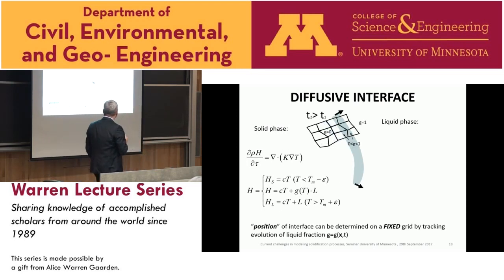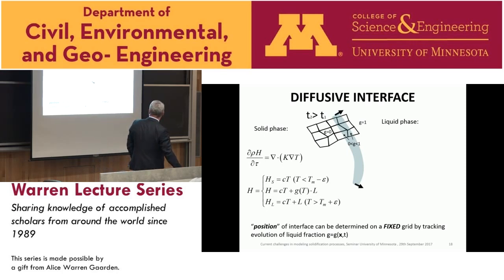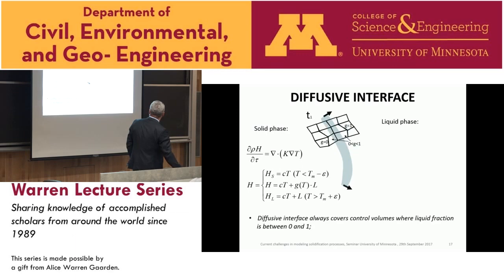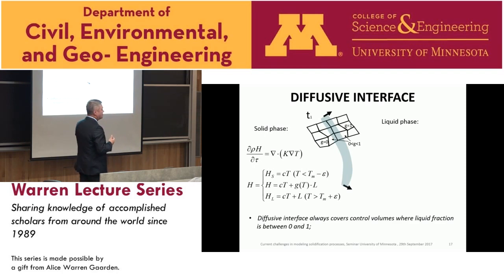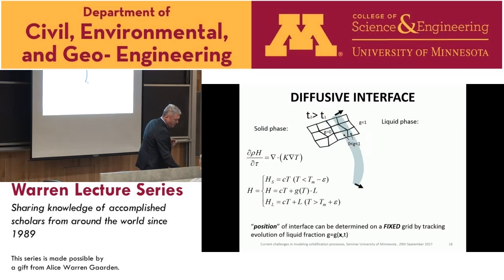You see? By just tracing those control volumes, we can see where the solid-liquid interface is. Instead of solving the complicated equation of heat balance between solid and liquid that I showed you, now we have a very simple solution to see where the solid-liquid interface is. So if we know how G looks, and if we calculate G in every control volume, we know where the solid-liquid interface is. Okay.